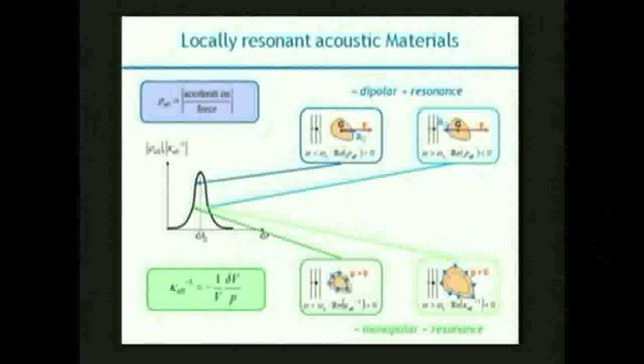Okay? And you can have exactly the same with what we call the monopolar resonance. So this is what we call a dipolar resonance in the first case, because you have a motion of the center of gravity of the inclusion. Whereas in the second case, down here, which is a monopolar resonance, you don't have motion of the gravity center of the inclusion, but you have rather an oscillation of the volume of the particle of the inclusion. And this oscillation of the volume of the inclusion with the incoming wave, in the case of a negative compressibility material, is when the oscillation is out of phase with the incoming wave. Is that okay?